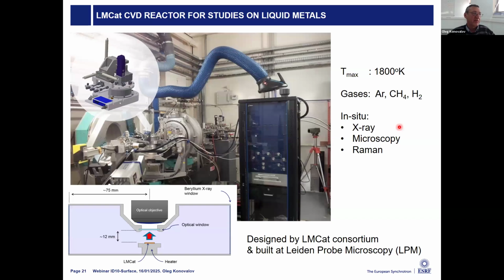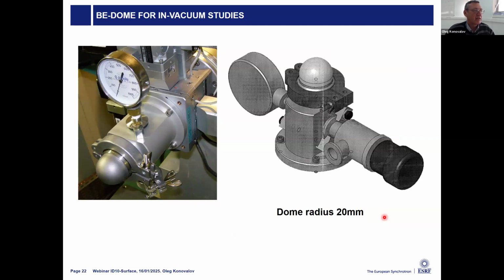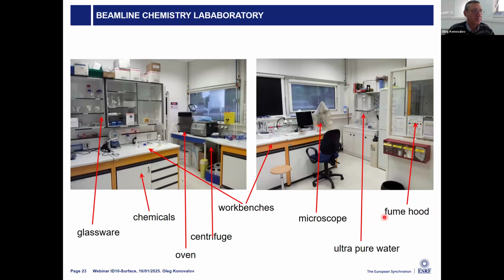And for several years already, we have another sample cell, a CVD reactor, to work on liquid metals, using it as a catalyst, for example copper, and then to go to the materials on that. This is how it looks in the experimental hatch. This box is here to control the gas flow through the reactor and also the heating. We can use different gases, and the temperature we can apply is a bit less than 2000 K. Also for some other things we have vacuum chambers for samples. We also have a chemistry laboratory close to the beamline, and a lot of things can be done here without the main ESRF chemistry laboratory.